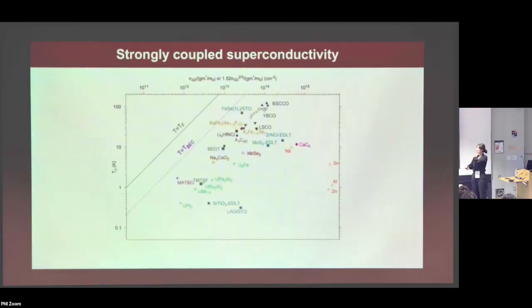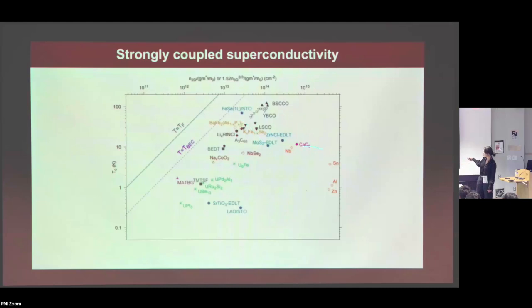So we have the strongly coupled superconductivity, and there's this thing called the Uemura plot, where you gather all of these different superconductors around the world. The x-axis is the electron density, similar to the ratio with the Fermi temperature, and the y-axis is the TC. So it tells you this ratio in one map. You can see that in the lower right corner, where you have large electron density but low TC, that's honestly not that efficient of a superconductor. You have these weakly coupled BCS superconductors like aluminum right here.